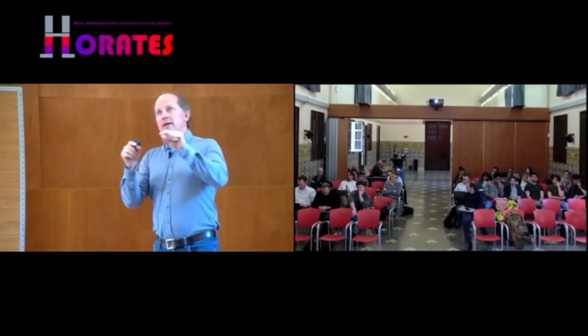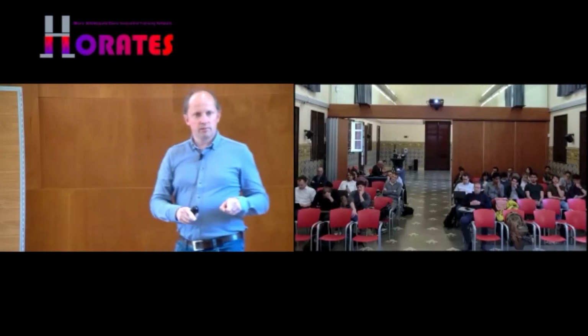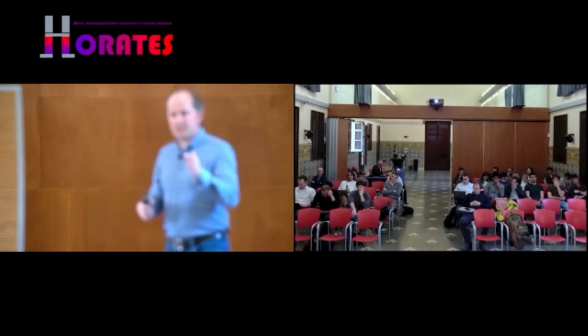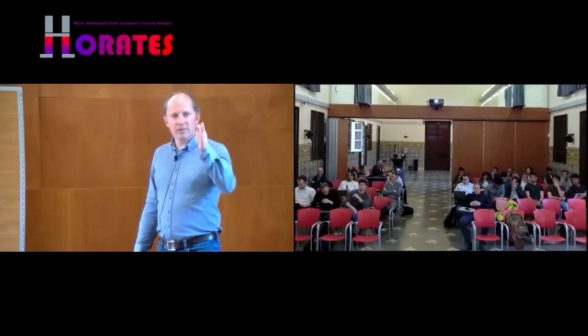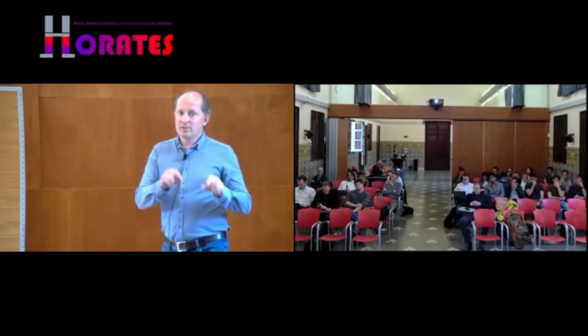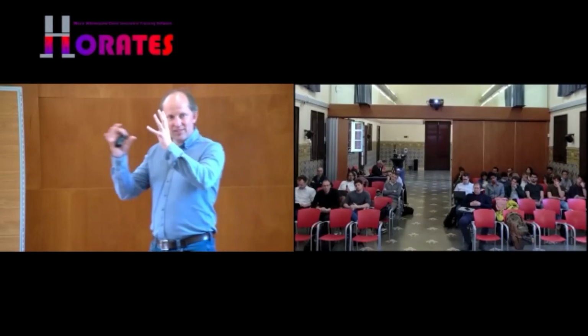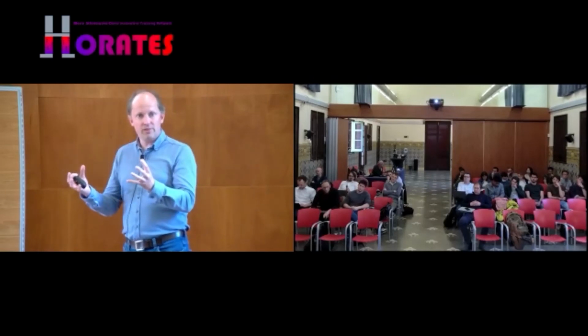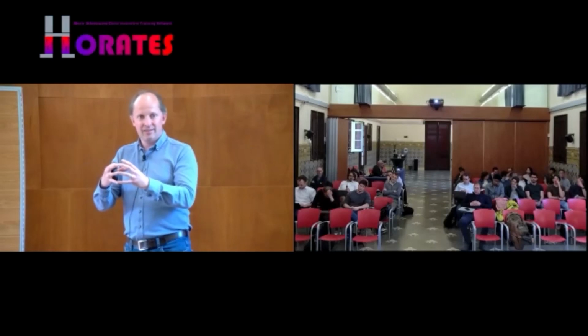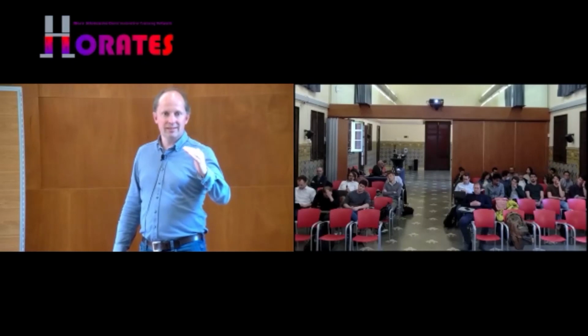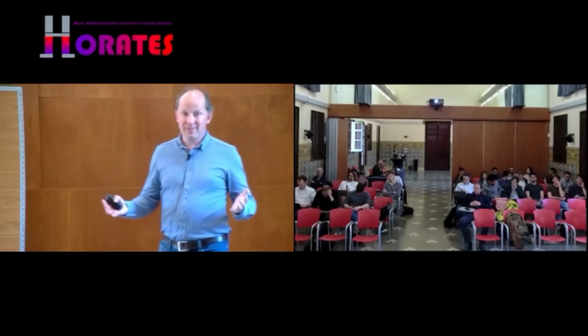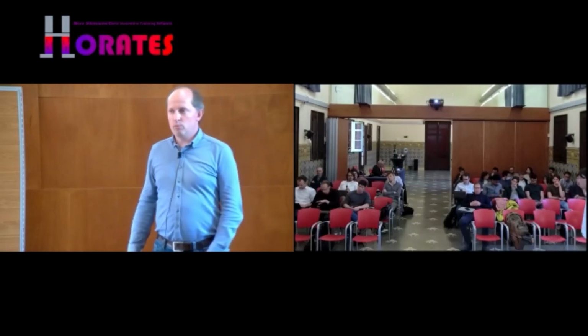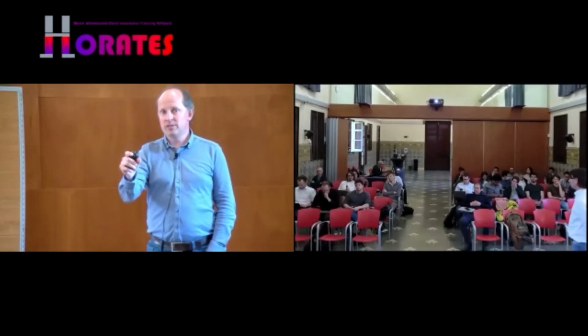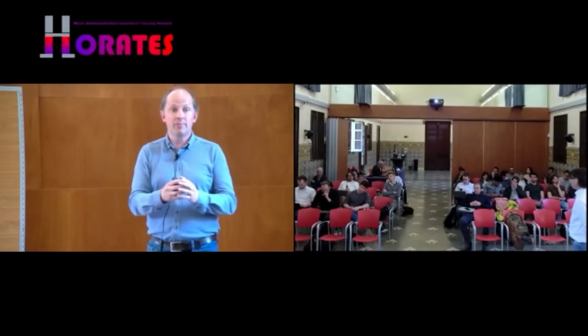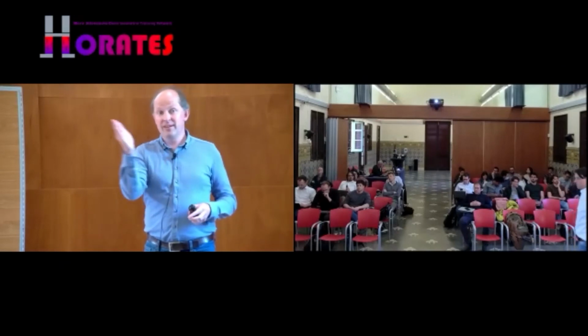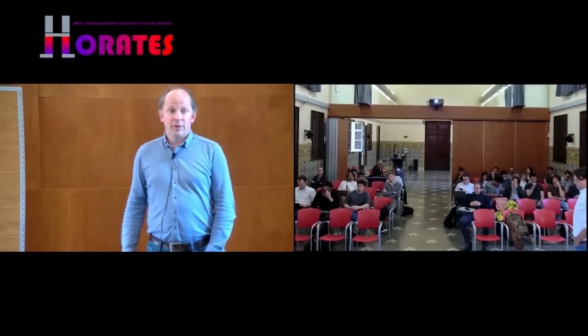The methylammonium, what I was looking at was the Kapitza resistance, the thermal boundary resistance, which seems to start to increase at the point where the methylammonium modes start to get excited. But that's only related to boundary resistance. Of course, that's not related to the bulk thermal conductivity of a crystallite. So within the crystallites, that's not being probed by the thermal boundary resistance. That's only probing what's happening at the edge. So I don't know what's happening at the edge. There's a lot of stuff happening at the edge, but that change in the thermal boundary resistance just seems to be at about the right temperature for the methylammonium to be doing something, as you say. Below that temperature, it's not really moving. Above that temperature, it's starting to move. But I can't pin it down 100%.